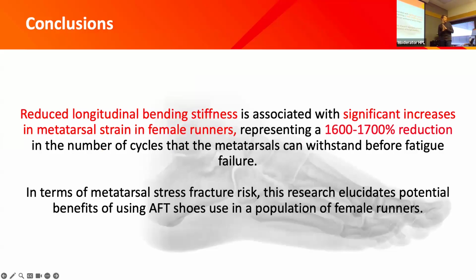So the conclusions from this work were that this reduced longitudinal bending stiffness shoe was associated with significant increases in metatarsal strain in the female running population, which represented about a 16 to 1700% reduction in the number of cycles that those metatarsals could withstand before fatigue failure. So when we frame this in terms of metatarsal stress fracture risk, this research potentially shows the benefits of using AFT shoes, at least for metatarsal stress fracture reduction in female runners.